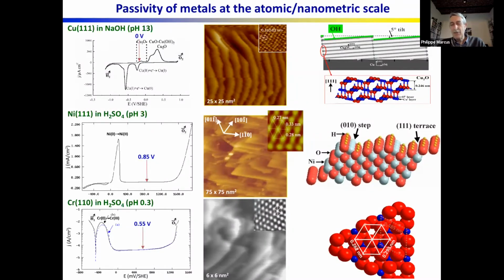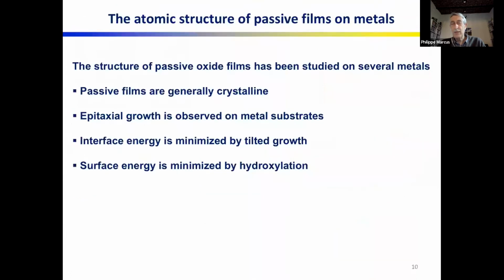So we can say that passivity is now fairly well understood at the atomic or nanoscale because it has been studied on several metals, not all of them, of course, but several metals. And some general features are expressed here. Passive films are generally crystalline. We observe epitaxial growth on metal substrates. Interface energy is minimized by the tilted growth of the oxide with respect to the crystallographic orientation of the surface, and surface energy is minimized by hydroxylation.